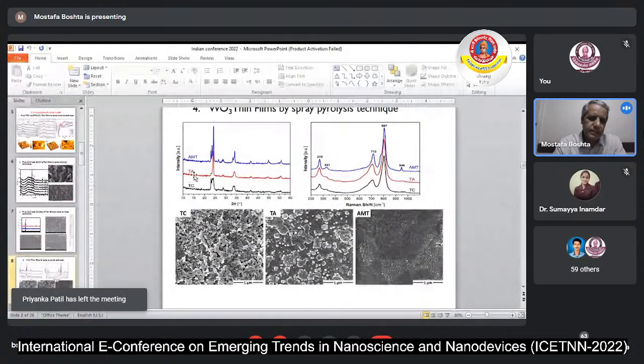So we tried to deposit tungsten oxide by spray pyrolysis from different source materials. As we can see here, there are 3 sources of material for deposition of tungsten oxide, and we have 3 different qualities or crystallinities between the 3 sources, but the crystallinity of all of them is almost close to each other, and the grain surface is a little bit different between the 3 sources, as we can see in the scanning electron microscope. So we will see which one of these materials can give us good efficiency and performance in the application after that.